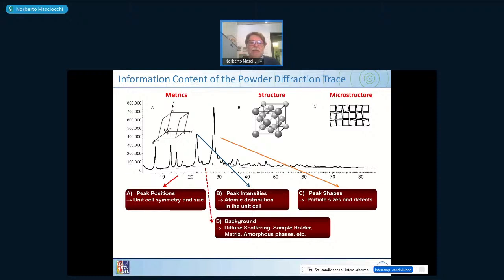Then peaks may not be very sharp; they can be wide, can have tails, or misplacement. This is called peak shape analysis or microstructure analysis, and gives information about non-ideal systems. A crystal structure is ideally infinite, but crystals are smaller than infinite, and if they are smaller than 1 micron, they show up as broadening of the peaks. Particularly if you also have mosaicity, that means the unit cells are not well aligned inside the crystal, then you have effects called strain, stress, and other properties which are important in the metallurgical fields.